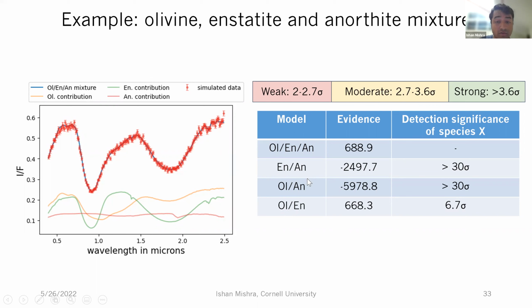So first we knock out olivine. We see that the evidence decreases significantly, meaning that olivine is very much needed, and that translates to a very high detection significance for olivine. Similarly, when we knock out enstatite, the evidence decreases much more, which translates to a high detection significance for enstatite.